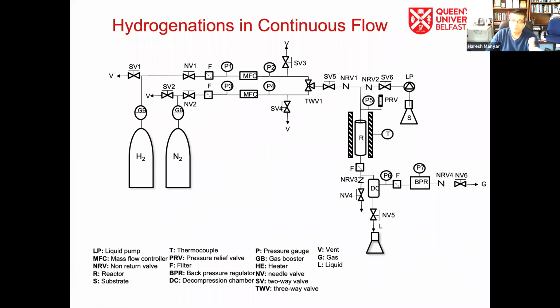But if you move towards a continuous flow and we do the hydrogenations in the continuous flow reactors, that is much better because now the catalyst will not be exposed and we don't need to recover the catalyst, wash it, dry it, and calcine it, and then again do the pre-reduction and lose all the metal-metal contact in that.